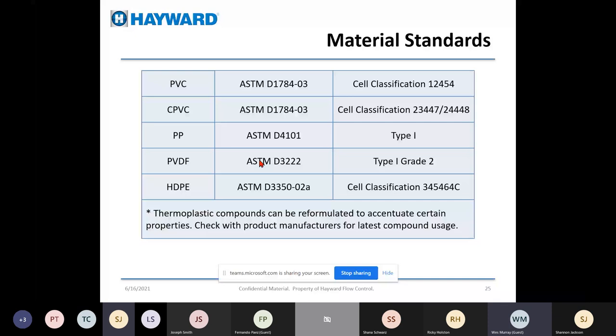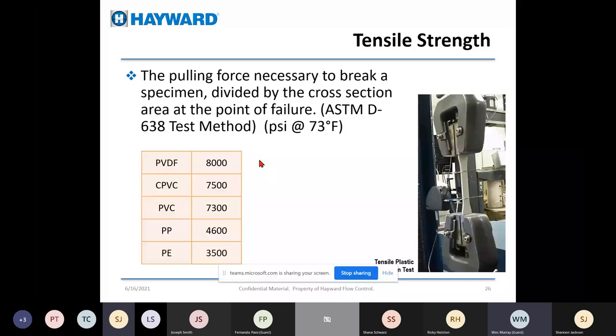This slide here just talks about some of the material characteristics, the testing that's done to create those ASTM codes. Tensile strength is a key one. We need to know failure points of materials so that as these sections of pipe and valves and things are installed out in industrial environments, we know how they fail. You can see CPVC holds up a little bit better than PVC. PVDF, which is a very expensive material, holds up a little better than CPVC.